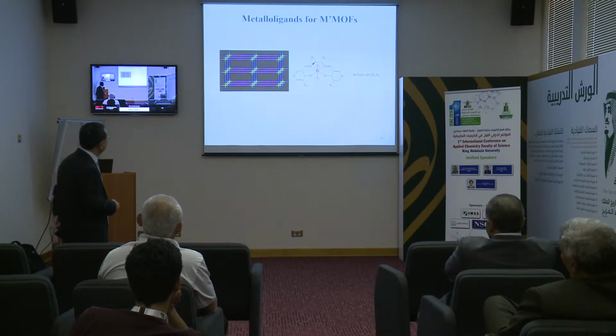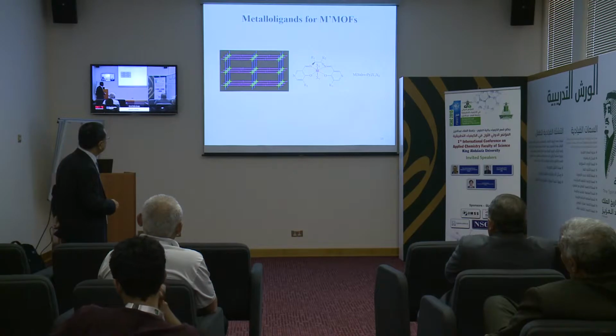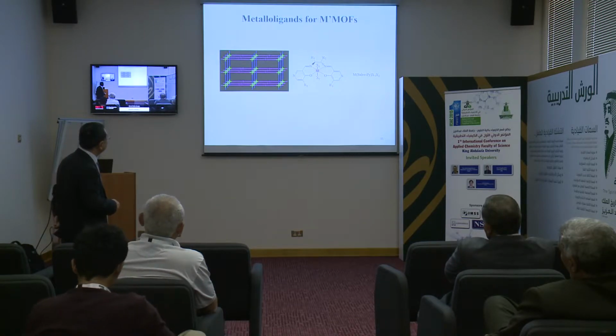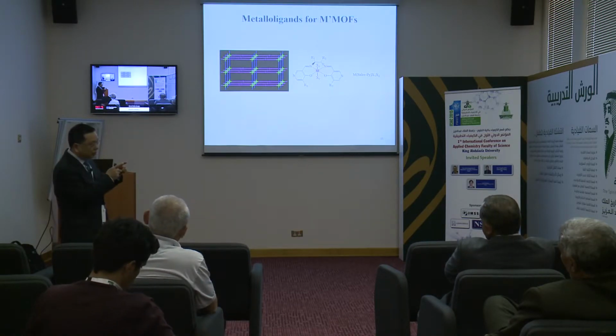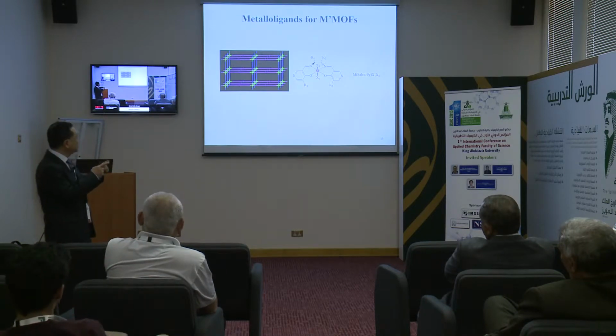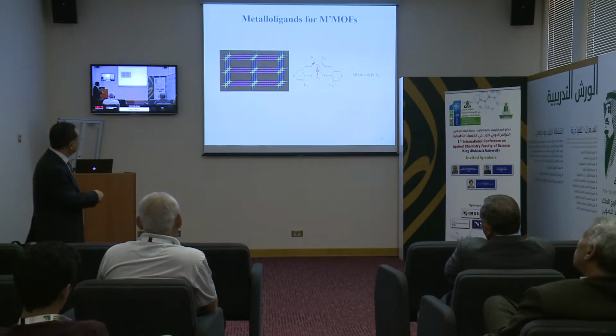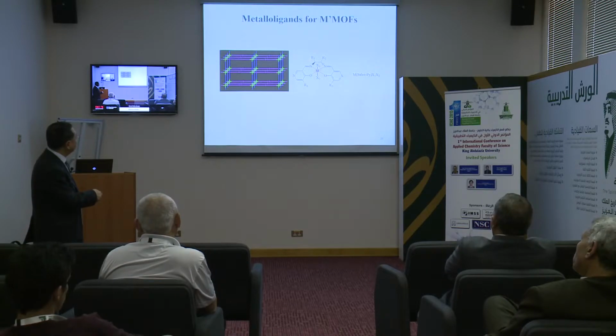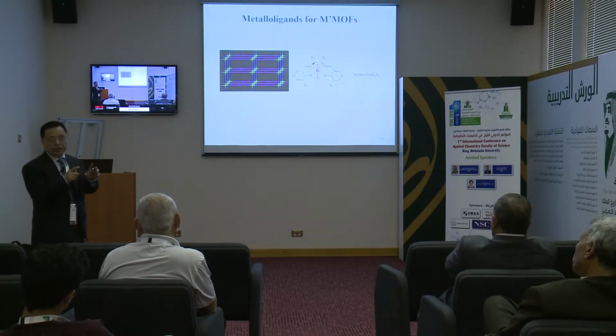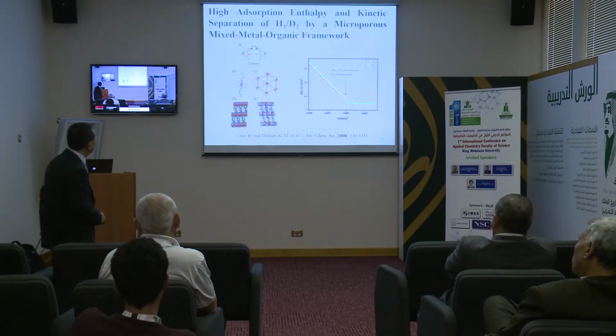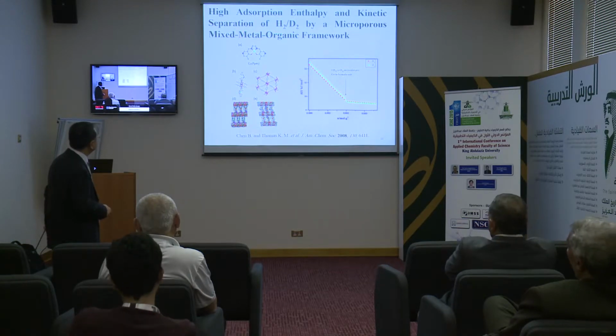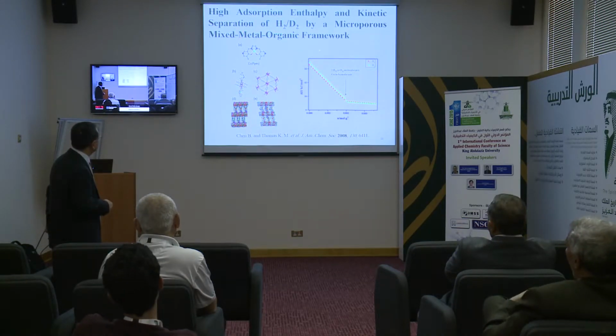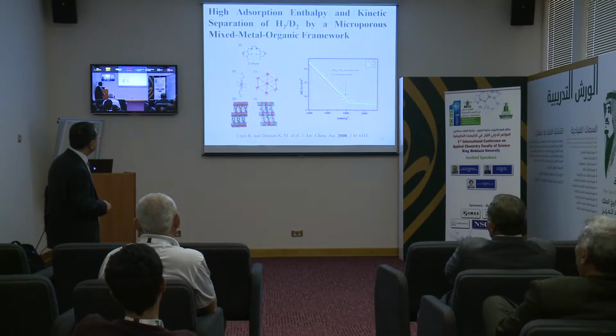And we also realized that these we call the metalloligands. This ligand has some uniqueness, with this open metal site and also this linker. This linker can finely tune the pore, because the pore is very important, fine tuning. And we can also incorporate this chiral diamine, so the pore is chiral, allowing for enantioselective separation. So this first example, we call the mixed-metal organic framework. And this work has some significance.